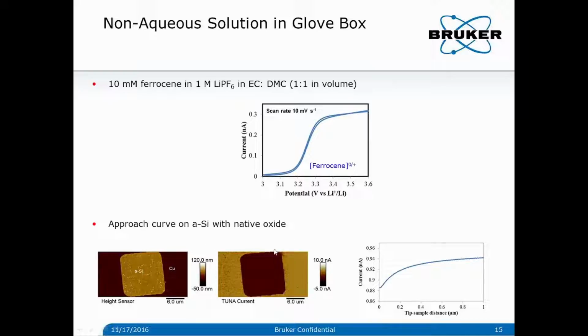So we use the same sample and run the feedback mode of the SECM in this solution with the ferrocene here, and you can see that we get an approach curve, and the negative feedback is as expected on the silicon surface because this is inactive.